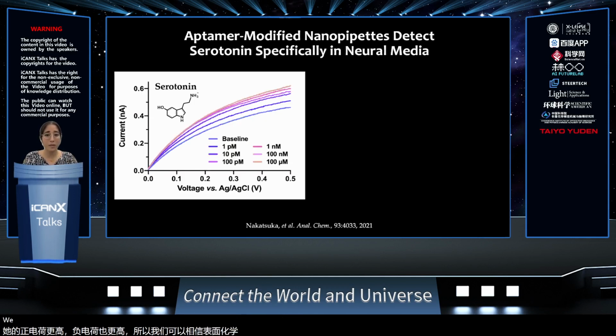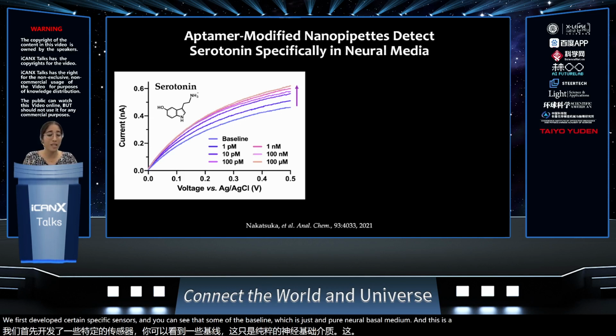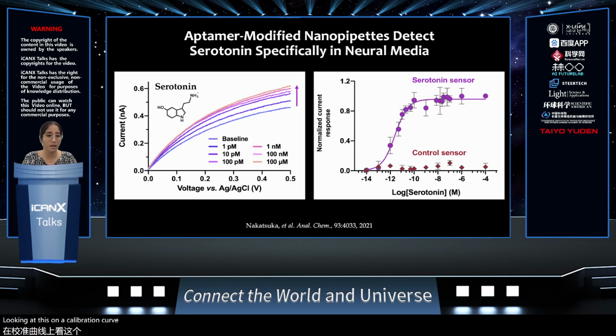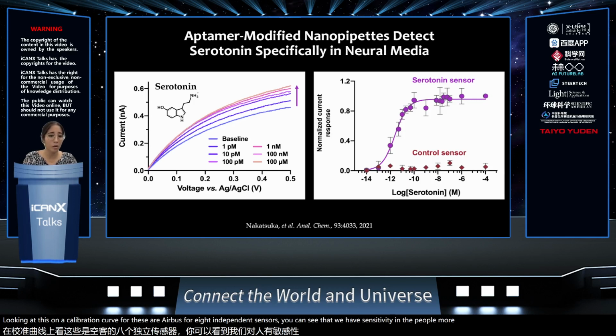We first developed serotonin-specific sensors, and you can see that from the baseline, which is just in pure neurobasal medium, a media in which neurons are cultured, so it's a complex environment, there's an increase in the current with increasing amounts of serotonin. Looking at this on a calibration curve, where these are error bars for 8 independent sensors, you can see that we have sensitivity in the picomolar to nanomolar range.